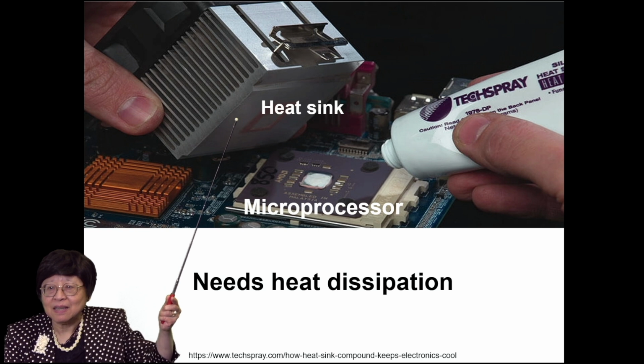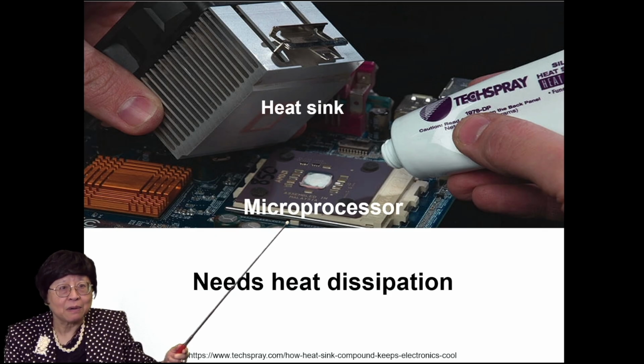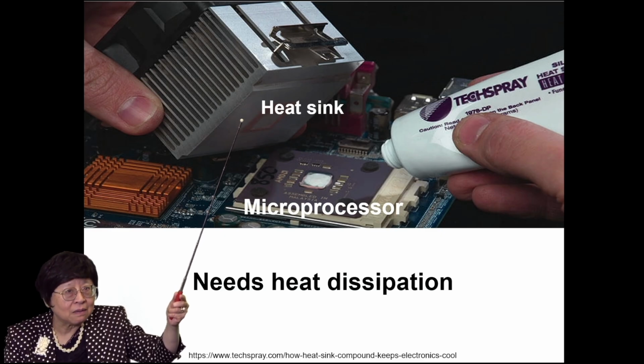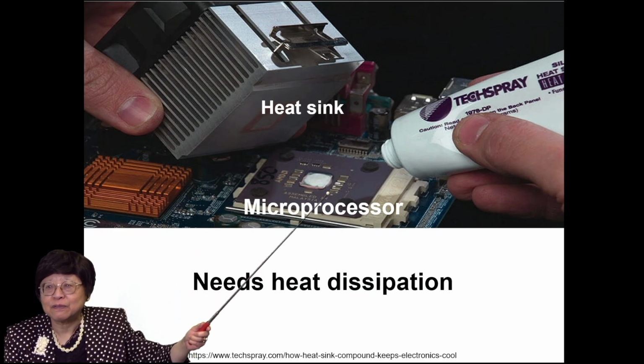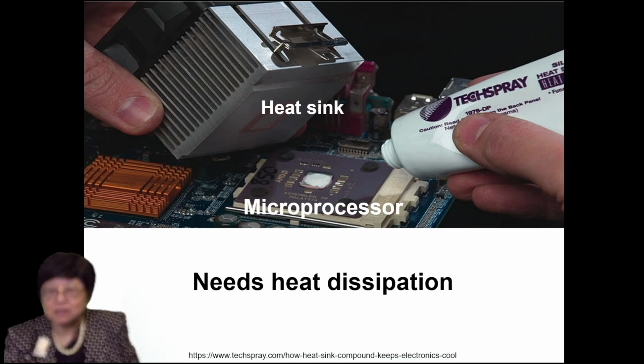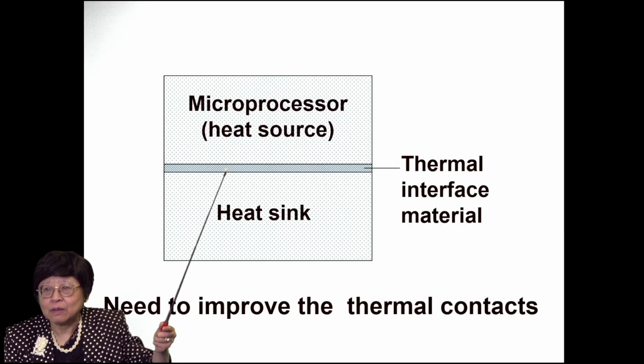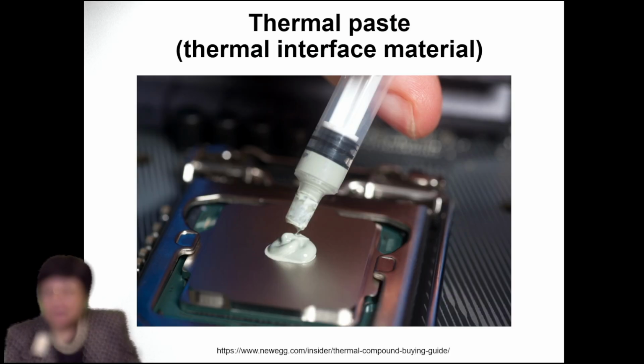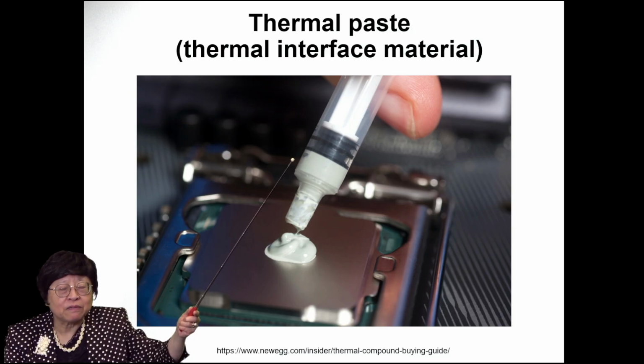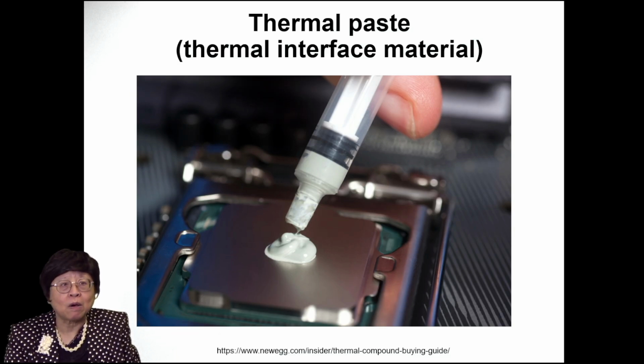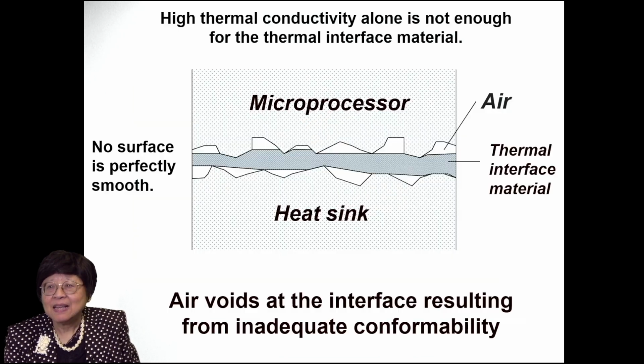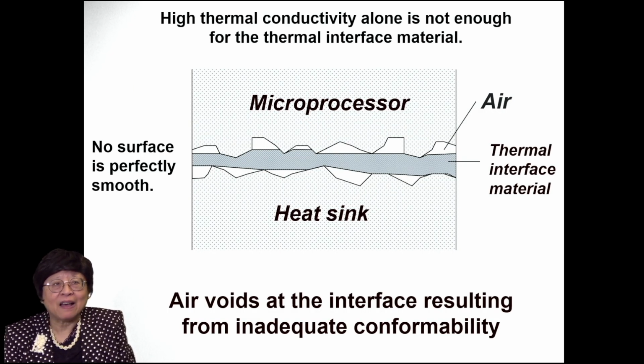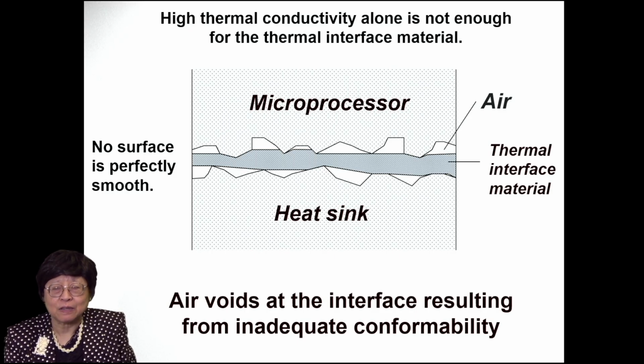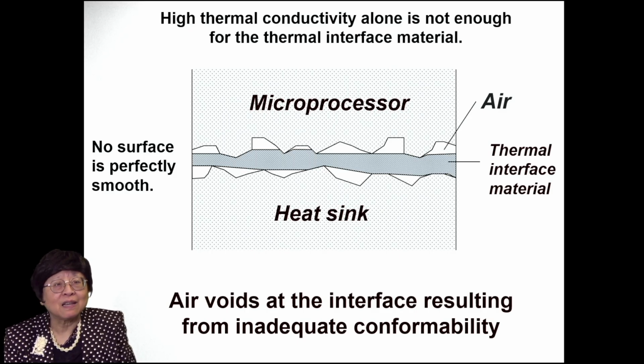We use the heat sink, obviously, but the thermal contact between the heat sink and the microprocessor can be a problem. If this thermal contact is not very good, you're not using the heat sink very well. So people put in a thin layer of thermal interface material at the interface so as to improve the thermal contact. And this is an example of a thermal interface material, which is in the form of a paste called thermal paste.